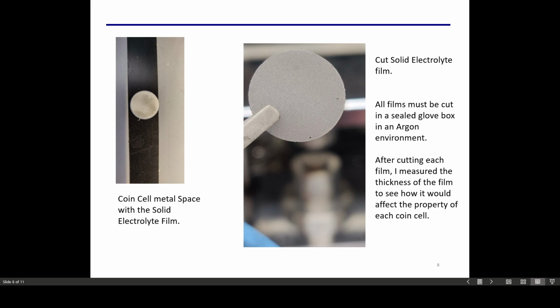On the left is a metal spacer with the actual cut film on it, and on the right is a picture that I took within the glove box of a film that I recently cut. And as you can see on the film, there are no imperfections, there are no impurities, and it is a nice circular disc. The films must also be cut within an argon environment in a sealed glove box, otherwise the lithium salt will react to the air.